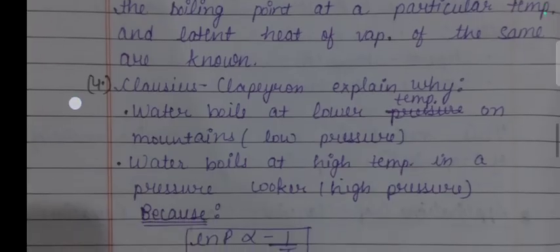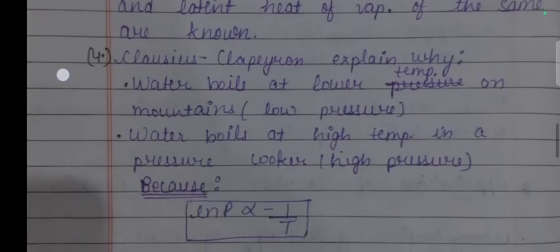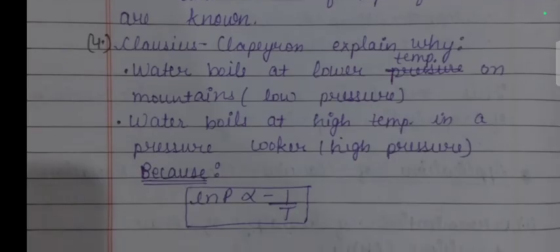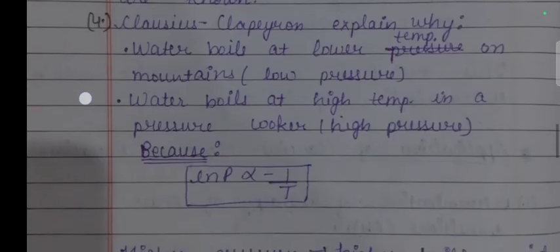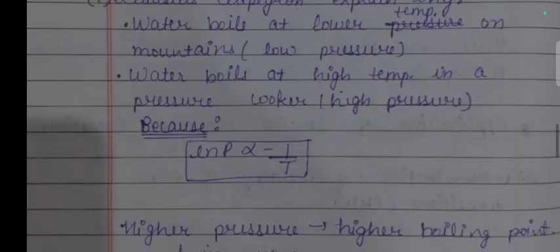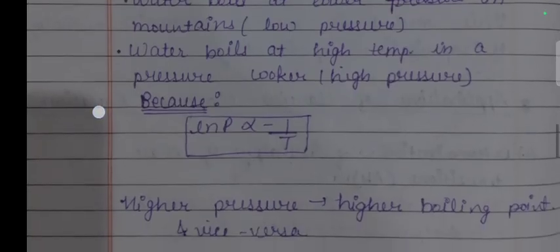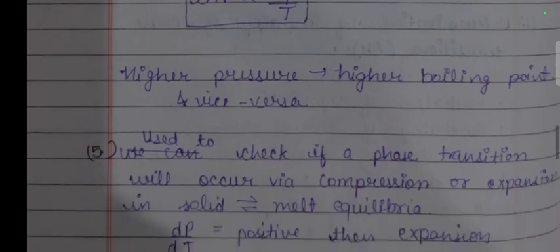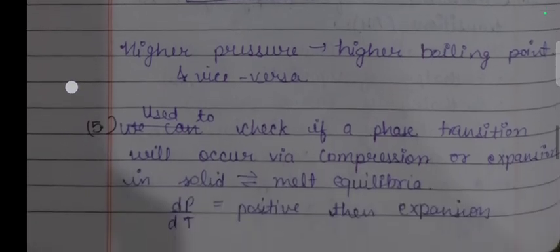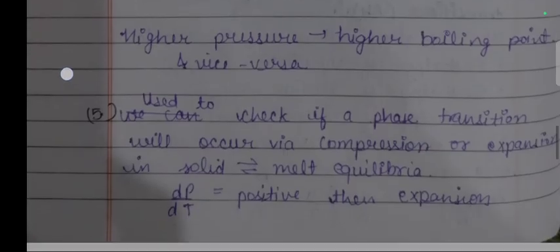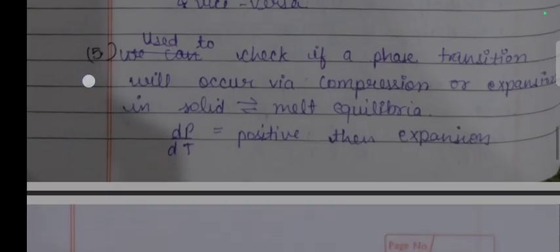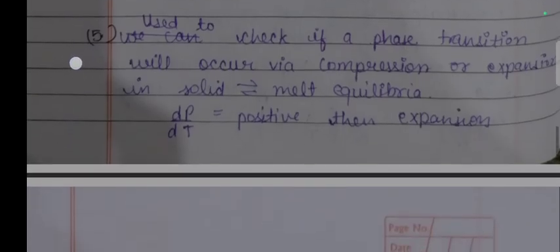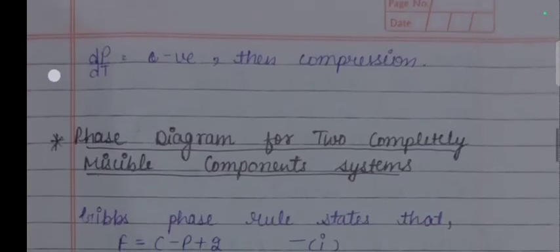Fourth, Clapeyron explains why water boils at lower temperature on mountains, low pressure. Water boils at high temperature in a pressure cooker, high pressure, because ln P is directly proportional to minus 1 upon T. Higher pressure means higher boiling point and vice versa. Fifth, used to check if a phase transition will occur via compression or expansion in solid in equilibrium with melt equilibria. dP upon dT is equal to positive when expansion. dP upon dT is equal to negative then compression.